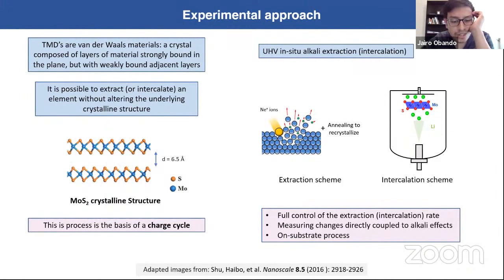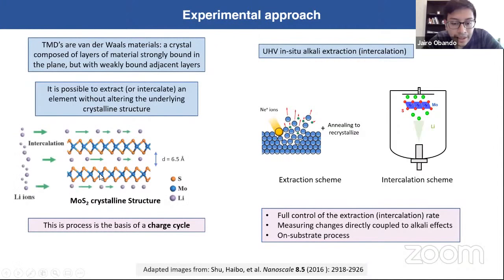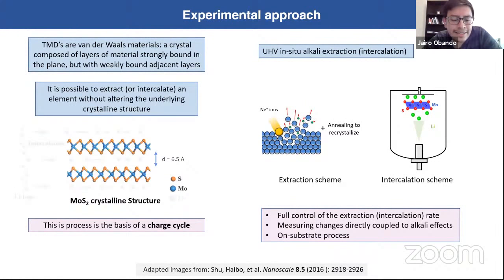This crystalline structure is a van der Waals type crystal, which consists of stacking two-dimensional layers of material strongly bound in the plane, as you can see here, and weakly bound along the stacking direction. This weak binding, in turn, allows for a lot of interlayer space, which is enough to accommodate charge-donating elements such as lithium or sodium. And it is this removal or intercalation of these elements that is the basis of the operation of charge and discharge cycles in a battery.